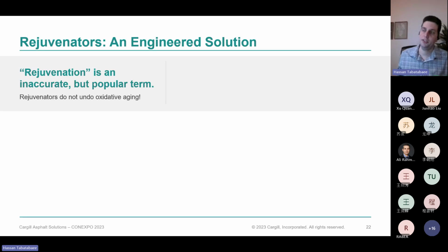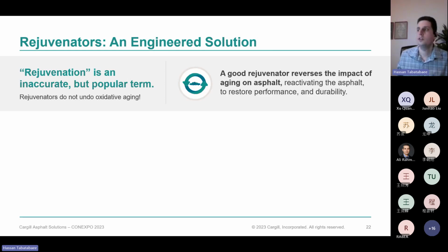So rejuvenation as a term is popular. It's a little inaccurate because it seems to imply that they are undoing oxidation. Rejuvenators are not chemically undoing oxidation. What they're doing is undoing, by a physical, chemical, more polar interaction, the impact of aging and oxidation on the performance, the brittleness, stiffness, and durability of an asphalt pavement.